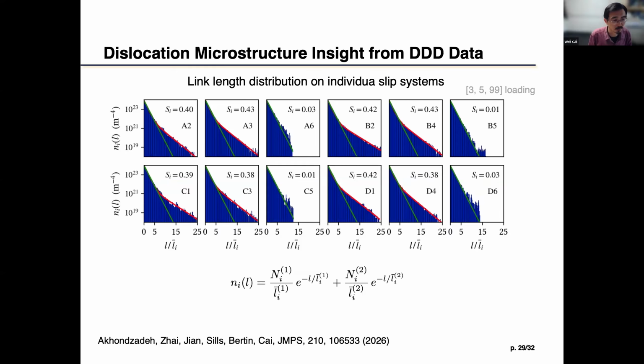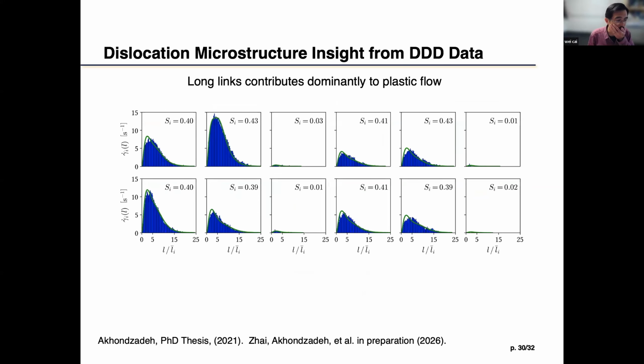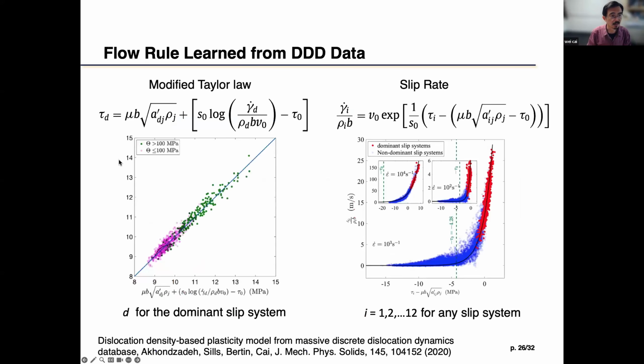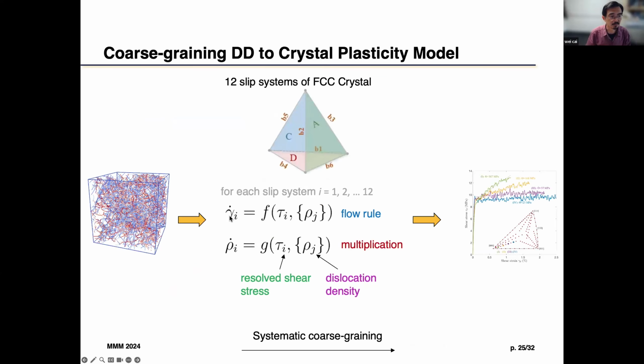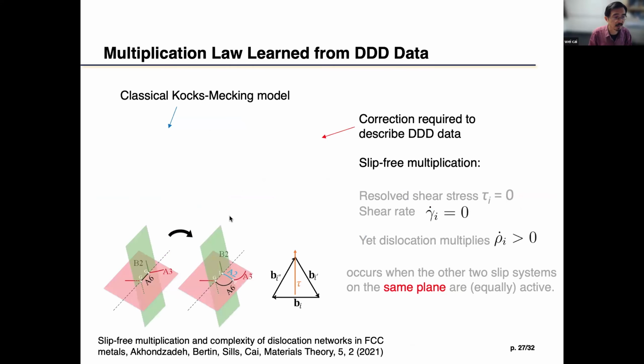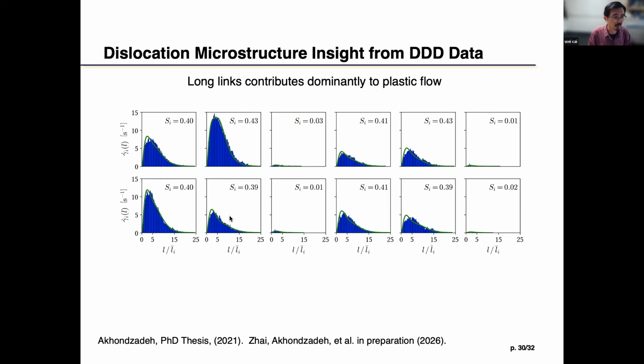We want to construct a flow rule. This is some of the work that was initially reported in Hamed's thesis, but we're still trying to pin it down. So the DD data can tell us not only what the slip rate is on every slip system, but also what the contribution to that slip rate is from links of different lengths. This is gamma dot, the same gamma dot as in here, but partitioned into contributions of links at different lengths. So the integral of that would be the gamma dot over there.